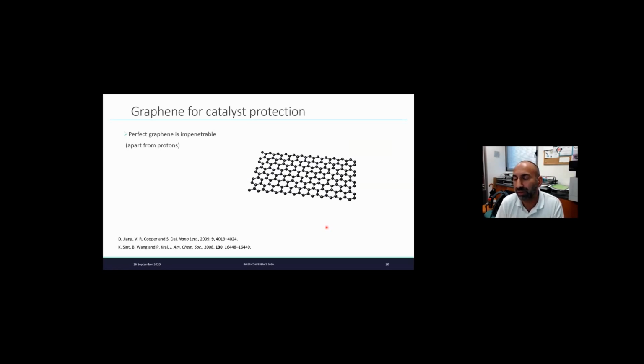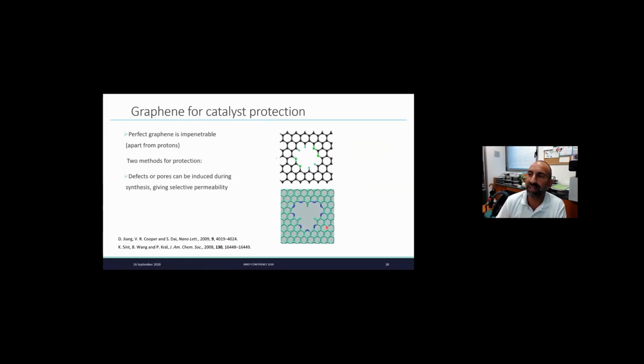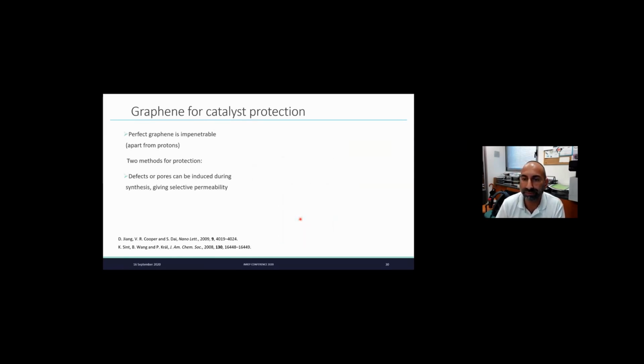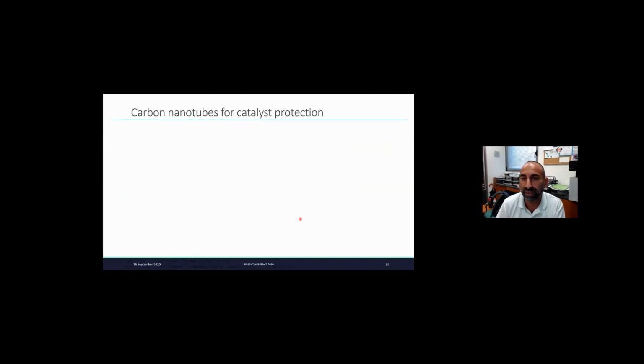So we know that graphene and carbon nanotubes are pretty impenetrable to hydrogen. Okay, hydrogen just rebound on top of the graphene. So if you want to make it porous to hydrogen, you need to create some defect, or you can create some pores, and you can do it by oxidizing the carbon nanotubes. So that's what we did. And carbon nanotubes are very good because they are very small and they confine the size of the particles. They don't grow during the operation of the cell.